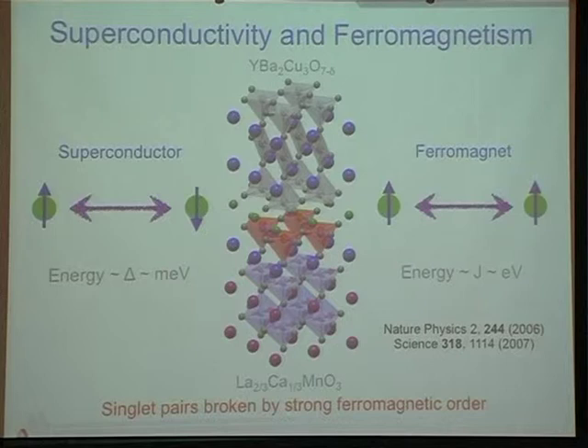So that was a case where I had a material that started with no orbital polarization, and I was trying to impose orbital polarization. The physics in all of those studies was very interesting. We enjoyed it. But one of the general outcomes was that if I have a material with a very large bandwidth, strain can only impose something like 100 millivolt splittings on the system. It's extremely hard to generate large orbital polarization. The prediction of superconductivity required 100% orbital polarization. In almost all of my experimental evidence, I'm getting something like 5 to 10%. So it's not going to cut it.